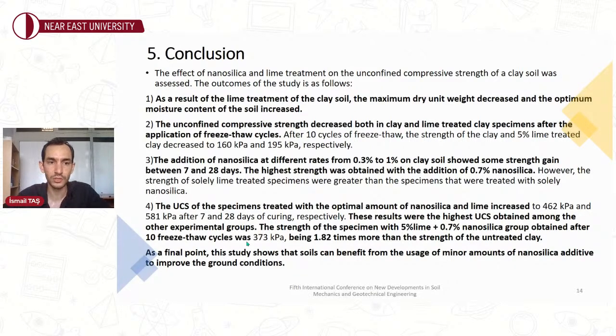However, the strength of the solely lime treated specimens was greater than the specimens that were treated solely with nanosilica. The unconfined compressive strength of the specimens treated with the optimal amount of nanosilica and lime increased. These results were the highest strength obtained among the other experimental groups. The strength of the specimens with 5% lime and 0.7% nanosilica obtained after 10 freeze-thaw cycles was 373 kilopascals, and this was 1.82 times more than the strength of the untreated clay.